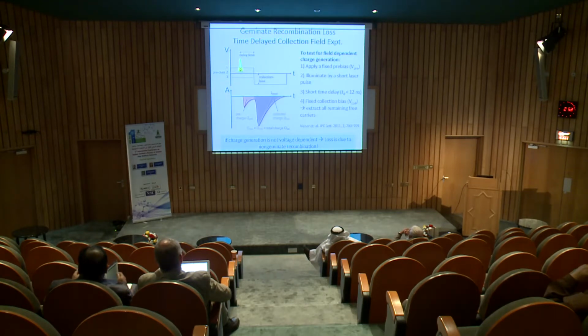Now to probe the geminate recombination loss in our two devices, the technique we use is called the time delayed collection field experiment, in collaboration with Dieter Neher in Germany. We make the solar cell device and apply a small bias, with the idea that if you have an electron-hole pair that is still bound to each other, applying a small bias can separate them. After that, we shine a short pulse laser on our device, wait for a certain delay time, and collect all the current generated by our device.